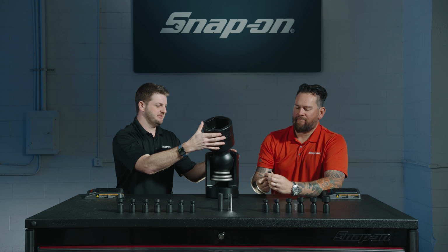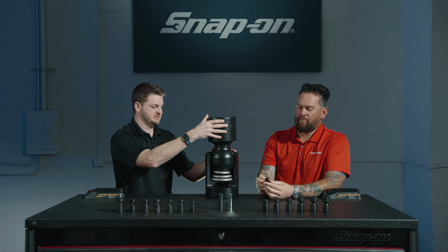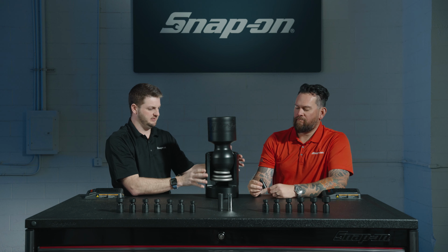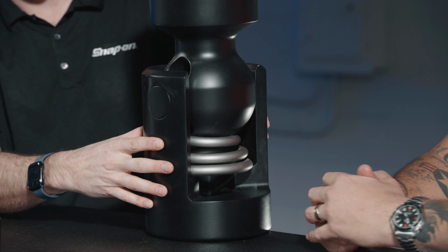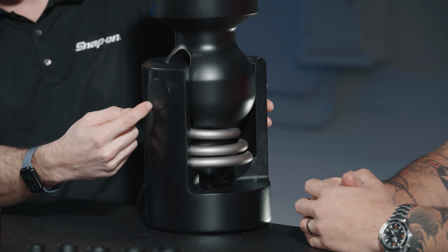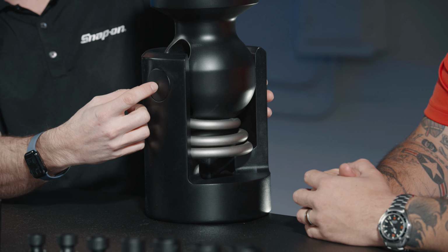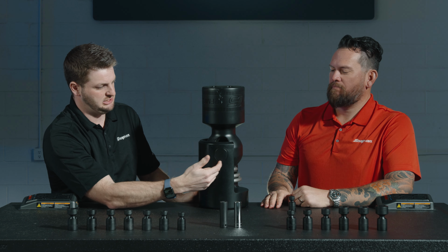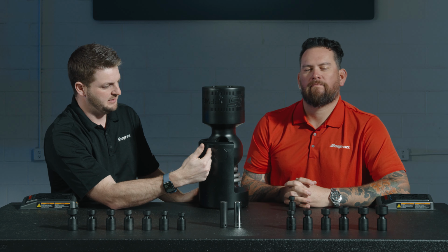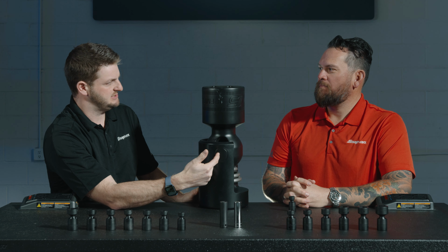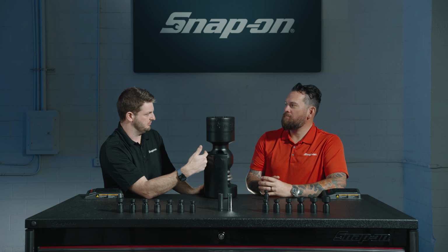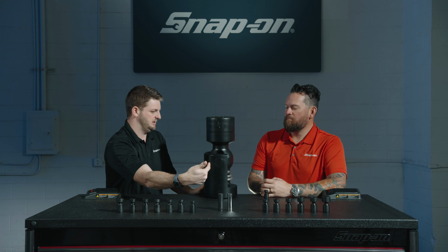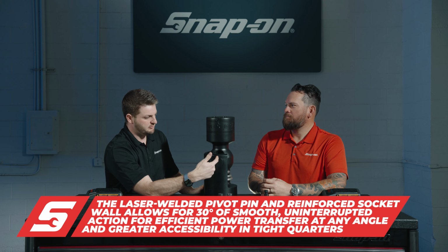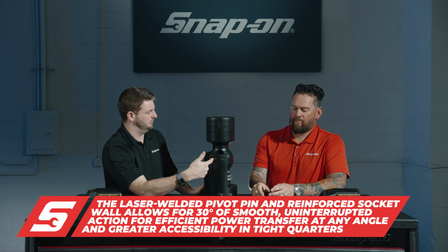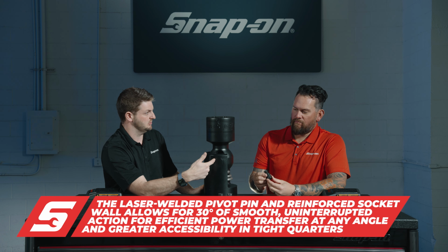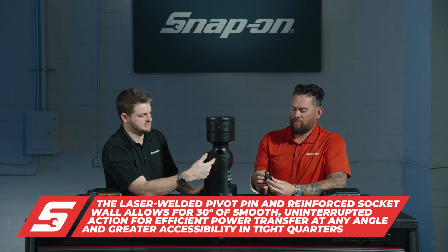Exactly. Another thing that really is the bread and butter of a socket and why we are so proud of this, I'll just rotate this here a little bit, is where the two ends are permanently joined together. We precision machine a hole through the drive end. We then take a high strength steel pin and put that through, right? So you drop the top, you've got the spring in there, run the pin through, and then we 360-degree laser weld this. This is a precision laser weld, and I talk about the precision because that's important.